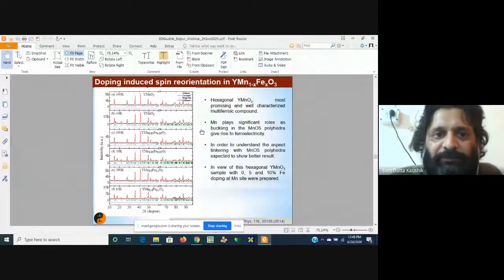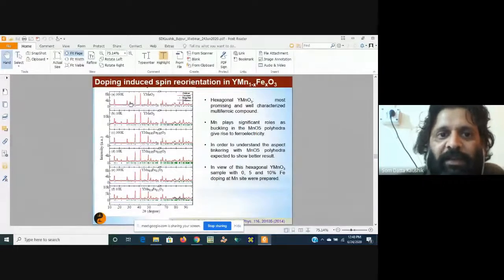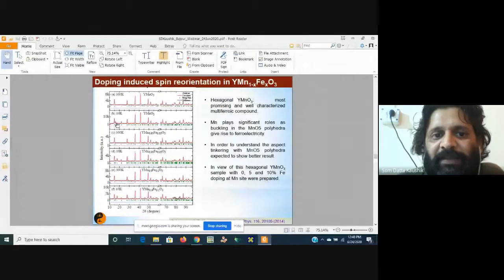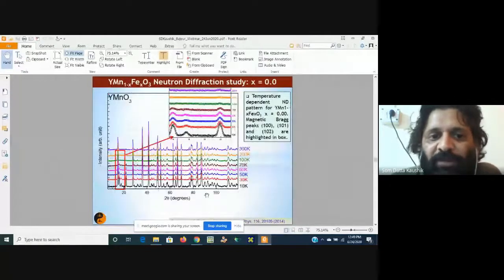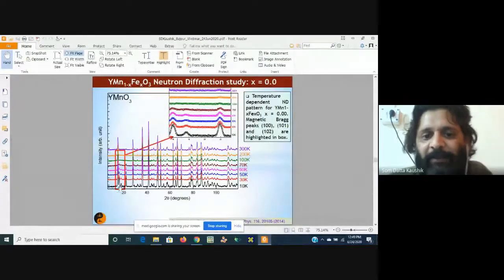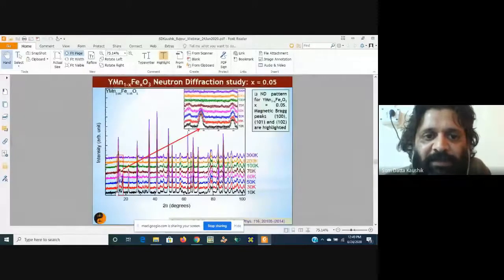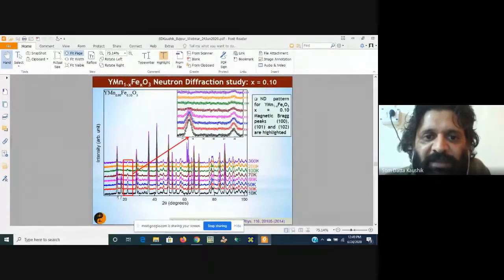This is YMnO3 sample, which is multiferroic in nature. So you can see at 10 Kelvin and 300 Kelvin. At 10 Kelvin, you see the magnetic peaks coming up over there. At 300 Kelvin, there is no magnetic peak. And upon doping iron at the Mn site, say 0%, 5% or 10% doping, you can see in these slides. For pure YMnO3, we can see the magnetic peaks coming over here. And upon doping the iron, you can see the magnetic peaks are changing their place.